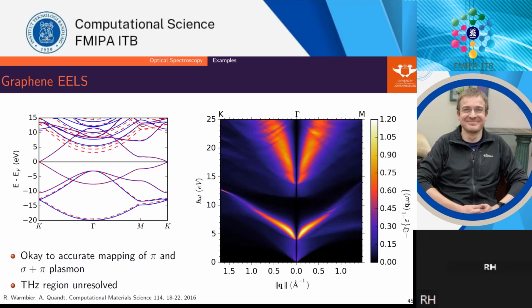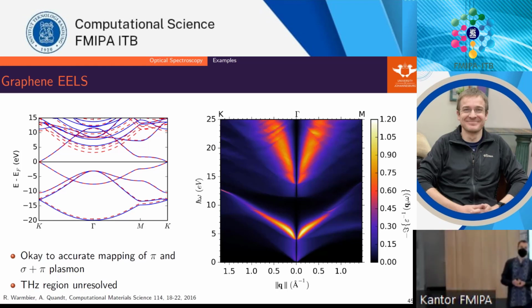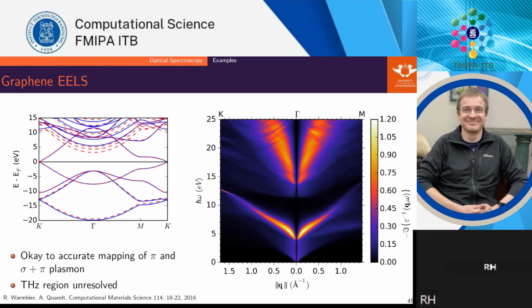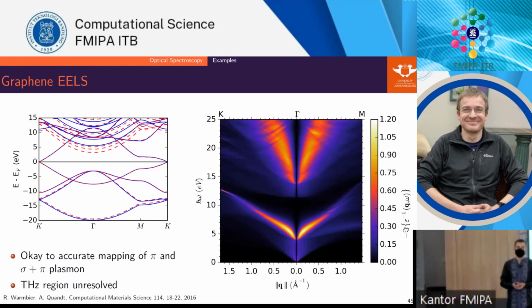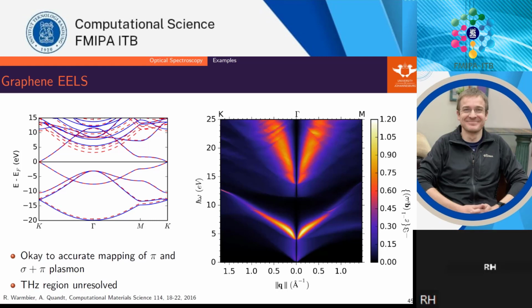Principally, also in our published paper, we think that the plasma frequency depends on the number of free electrons. And we found that the number of free electrons is small, and that's why the plasma frequency is in the terahertz region, not in the UV like in a metal. Right. Okay.